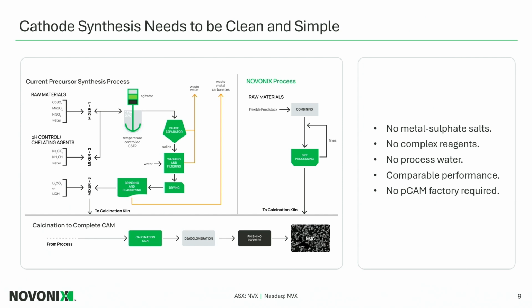The Novonix process, the all-dry zero-waste process, by contrast, is a huge simplification. We're beginning with flexible feedstock. We're talking metal powders, metal oxides, metal carbonates, and we combine those in a process we call all-dry zero-waste. There may be a little bit of pretreatment, there may not, depending on the chemistry that we're making. But at the end of the day, that combined product is fed into the calcination process.